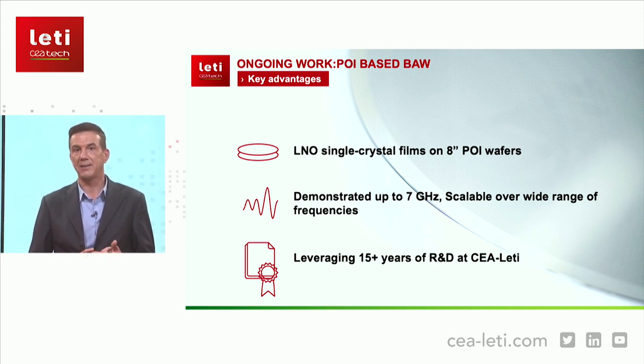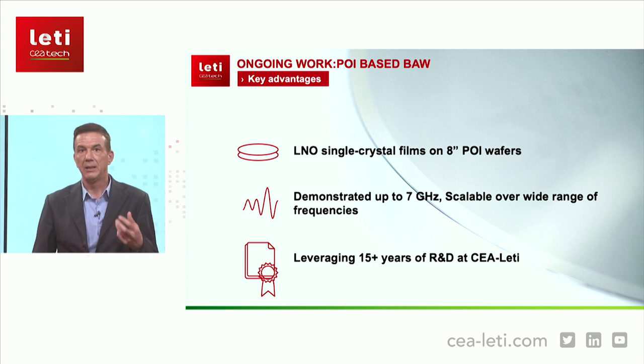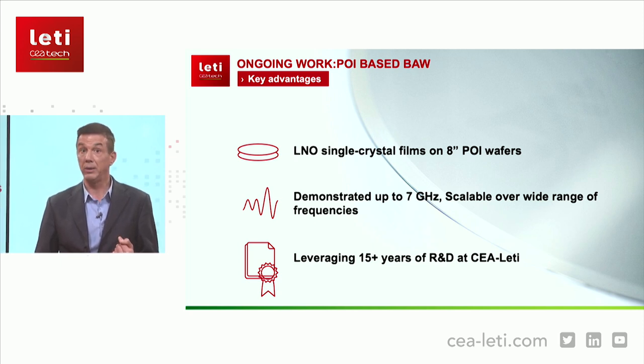Second, you get this nice monocrystal served on an 8-inch silicon plate, so to speak. This means that standard semiconductor deposition, patterning, and etching equipment can be used for manufacturing. Leti has thoroughly studied the manufacturing process of this device using standard production-grade equipment. We believe that our process can achieve high yields in volume production.